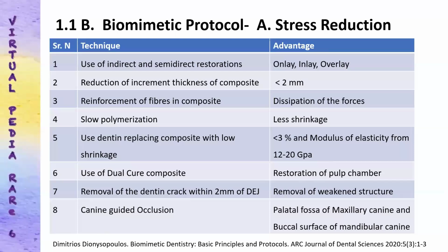The reduction in the increment of thickness of composite will always reduce this shrinkage or the stress which is formed after the restoration of the composite. The fiber reinforced composite at the dentine level also helps us to dissipate the forces of the occlusion. Slow polymerization by light cure unit in a ramp or intermittent pattern will also reduce the stress concentration in the composite. The dentine should always be replaced by a flowable composite rather than a condensable composite.